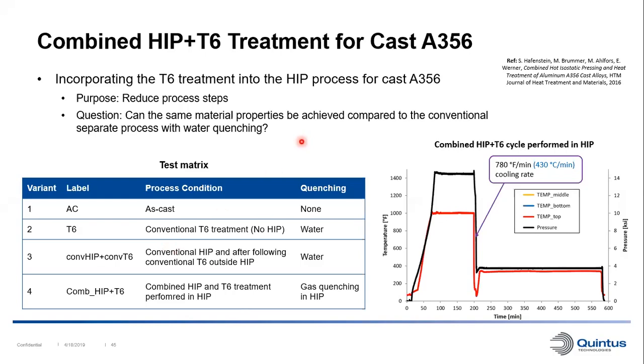And in the matrix down here, we can see the different variants. So we had one as-cast variant, we had a variant that was cast and then conventionally heat treated with water quenching. Then we had a material that was conventionally HIP'd and then afterwards conventionally heat treated with water quenching, the full heat treatment. And the fourth variant was a combined HIP and heat treatment where we performed everything in the HIP.